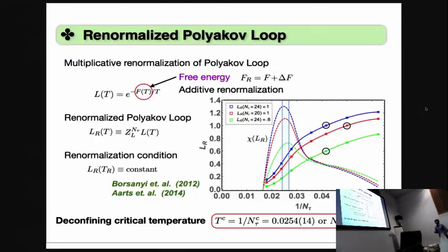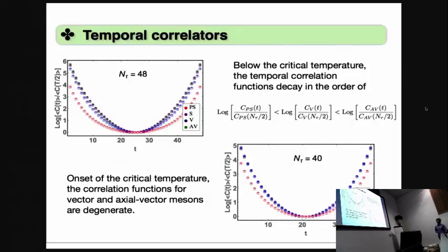Okay, so we determine the critical temperature by looking at the Polyakov loop. The Polyakov loop receives multiplicative renormalization, so we impose the condition that the renormalized Polyakov loop at a given reference temperature is constant. For this calculation, we use three different reference points and look at the peak of the susceptibility of the Polyakov loop, assigning the error from these different renormalization conditions. We found that N_tau critical equals 39.5, or T_C equals 0.0254 in lattice units.